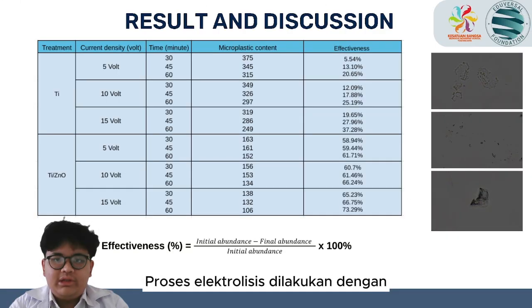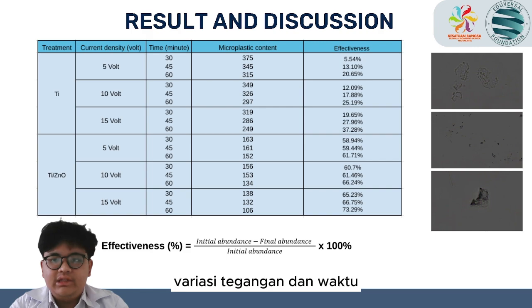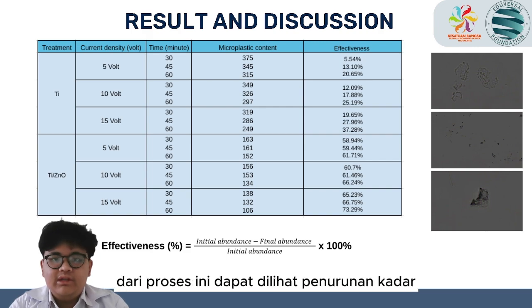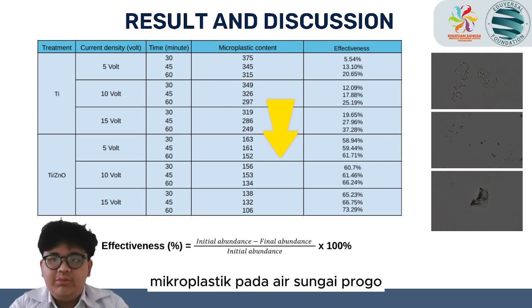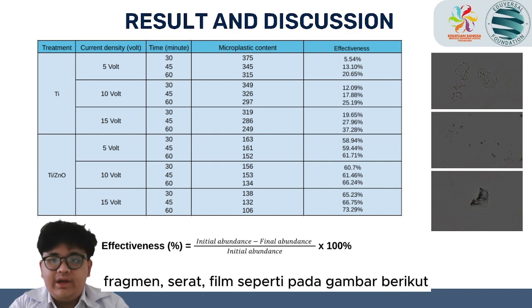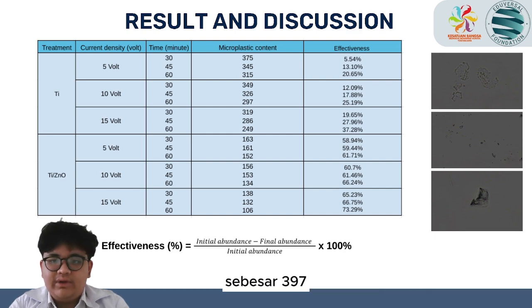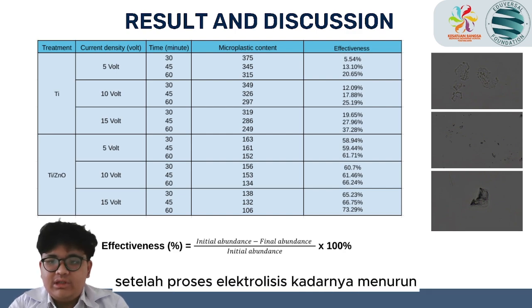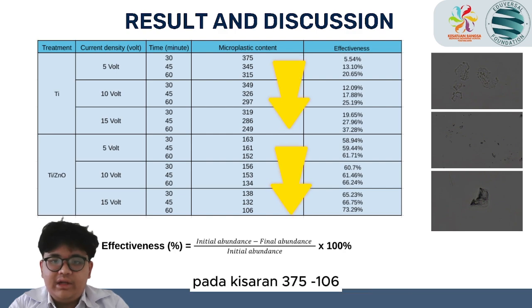The electrolysis process is carried out with variation in voltage and time. From this process, we can see a decrease in microplastic level in Progo River water. The observed microplastic consists of fragment, fiber, and film as shown here. The microplastic content before the electrolysis was 375. After the electrolysis process, the content decreased in the range of 375 until 106.